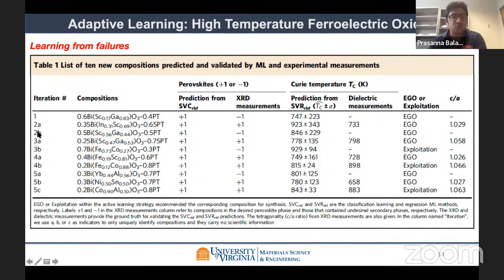And then we came up with the next set of predictions. As a result, you have 2A and 2B. 2A is a new composition that the algorithm recommended, which is a little different from the previous composition, and we also wanted to keep track of the previous composition. So in the second iteration, we had two recommendations, but the relative concentrations were a little different. We were trying to see whether our model can learn why it failed and adaptively change the decision boundary.